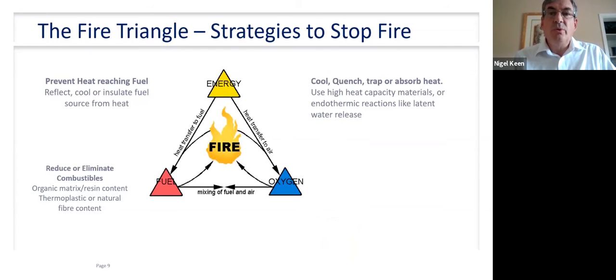We can cool, quench, or trap the heat. So if we can use high heat capacity materials or materials that will give off water as they decompose, so things like aluminium hydroxides will actually decompose when they get to 180 degrees, 200 degrees. So before everything really starts to take off, you're actually quenching the heat by providing water that will vaporize to steam.